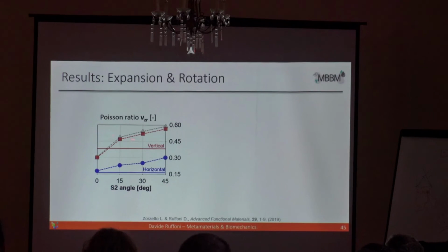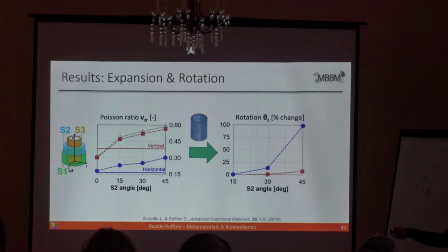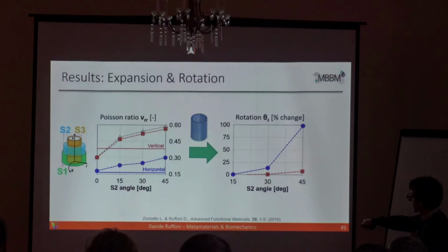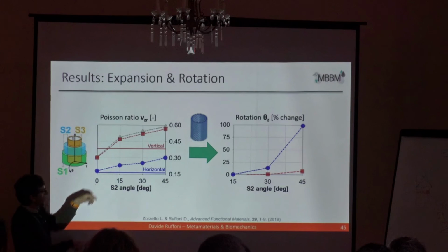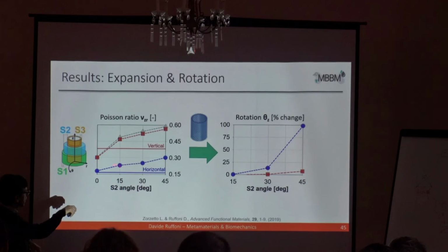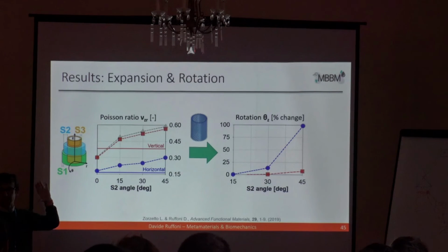And okay, this I think I skip because it's not so interesting. And what we see also in terms of mechanical behavior, thanks to finite element analysis, is the following. See the Poisson's ratio of those systems, so the lateral expansion when we apply a compression. Sorry, I forgot to put the legend here. So this gray here is the system with no reinforcement, so it's just the simple cylinder. And what we see is that by increasing the winding angle of the fiber, the system expands more laterally when we compress it. This is what we see here.